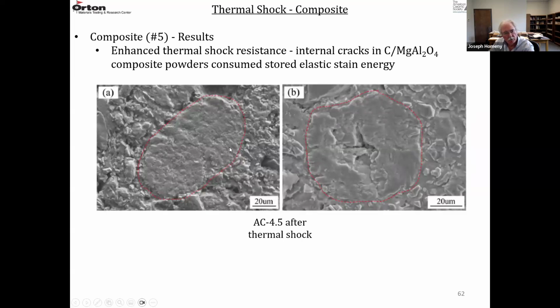So this is an area of one of those powders. So this is a graphene carbon spinel powder outlined here. And this is before thermal shocking, and then this is after thermal shocking. So they're saying, well, these powders that contain the graphene, these composite powders, are consuming more of the stored elastic strain energy by fracturing. So they're fracturing internally, dissipating stored elastic strain energy.